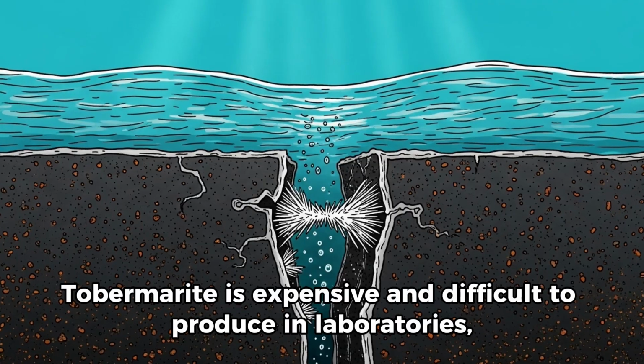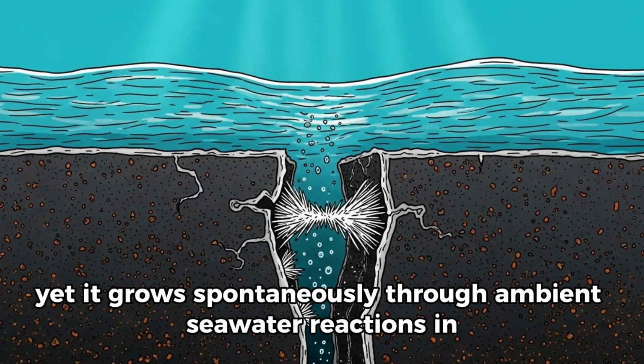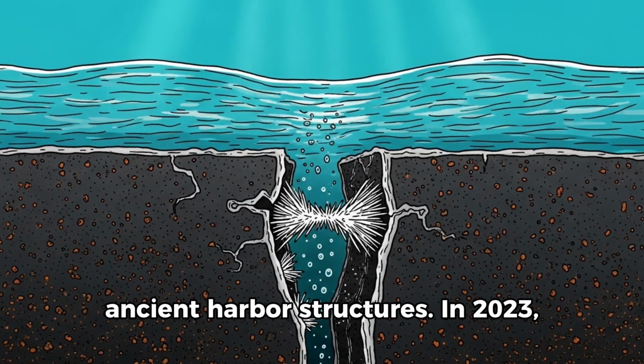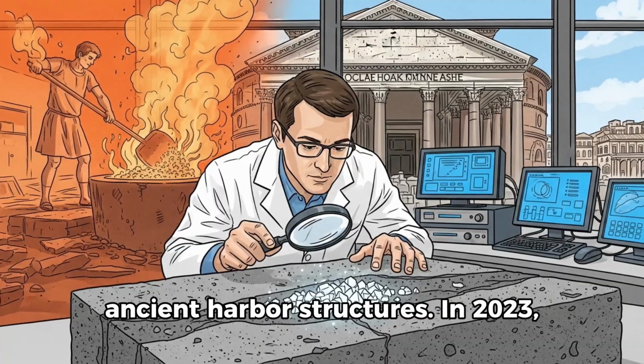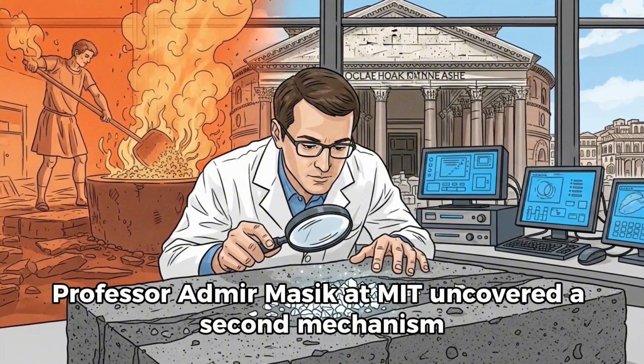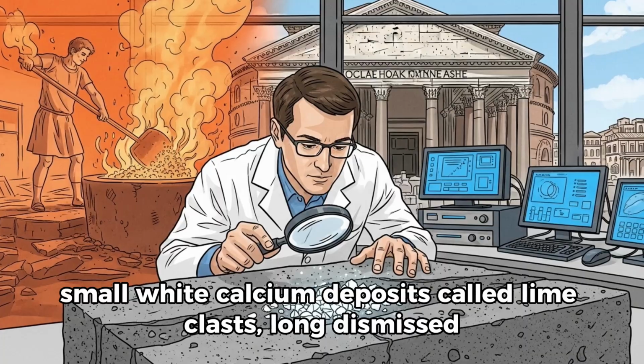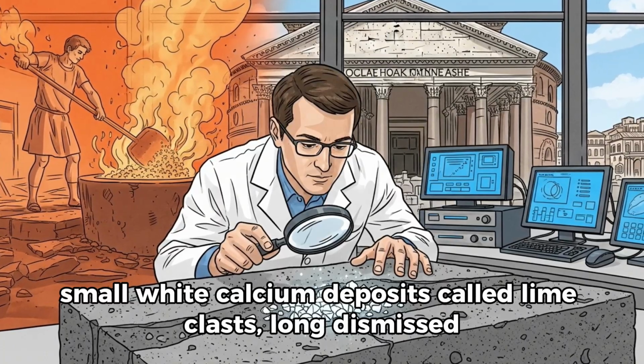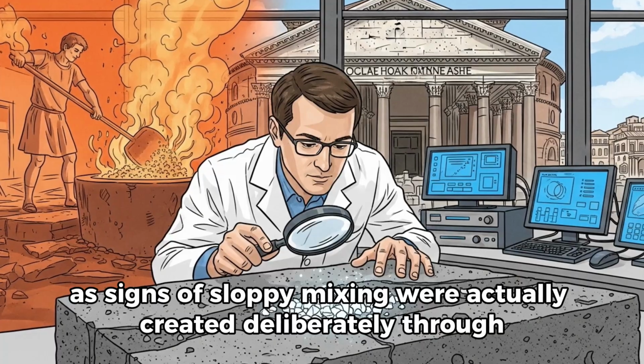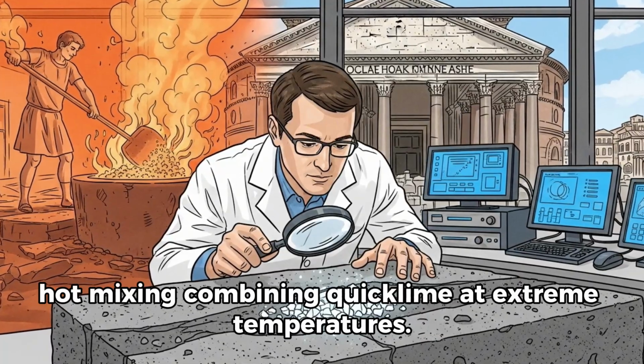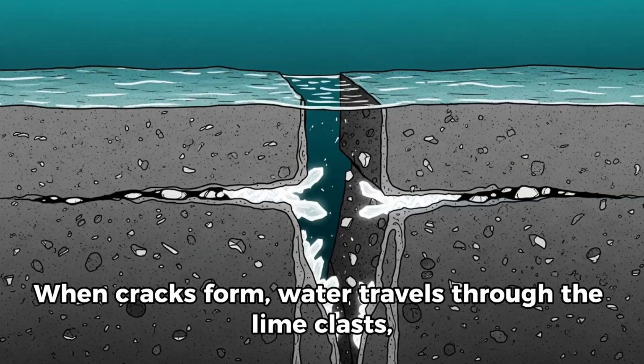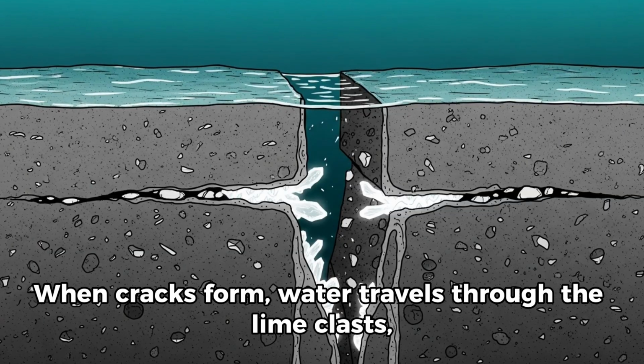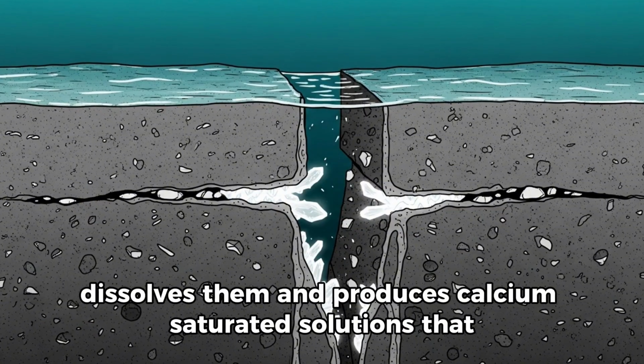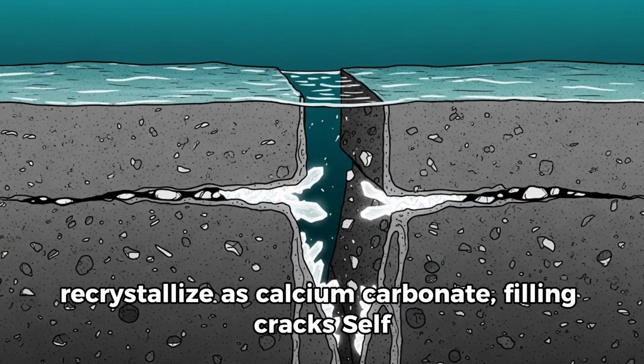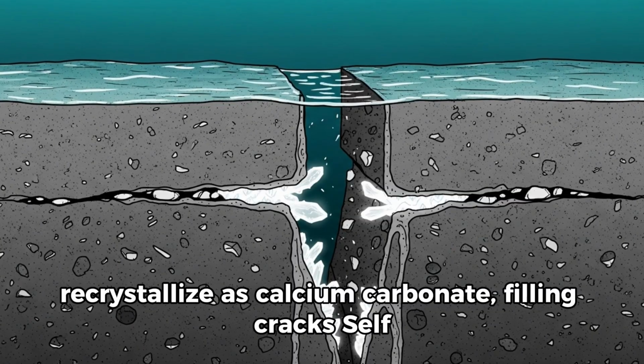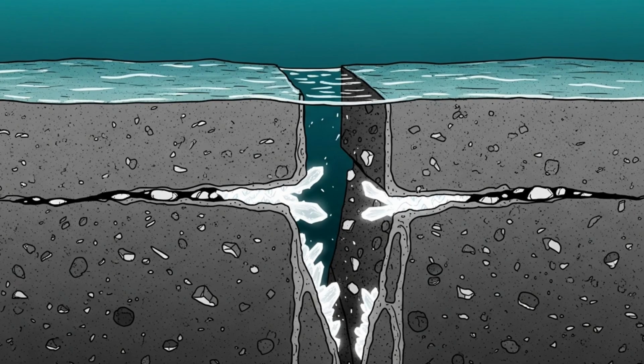Tobermorite is expensive and difficult to produce in laboratories, yet it grows spontaneously through ambient seawater reactions in ancient harbor structures. In 2023, Professor Admir Masic at MIT uncovered a second mechanism. Small white calcium deposits called lime clasts, long dismissed as signs of sloppy mixing, were actually created deliberately through hot mixing, combining quicklime at extreme temperatures. When cracks form, water travels through the lime clasts, dissolves them, and produces calcium-saturated solutions that recrystallize as calcium carbonate, filling cracks. Self-healing. Within weeks.